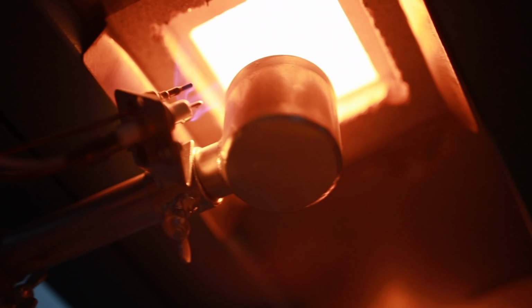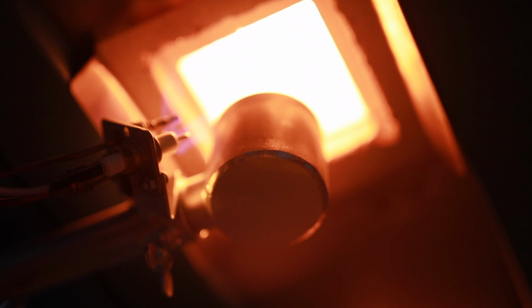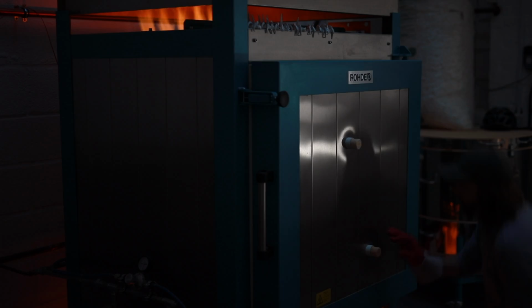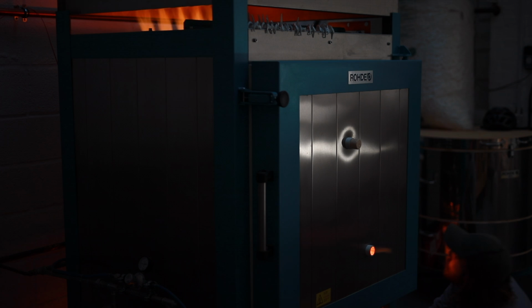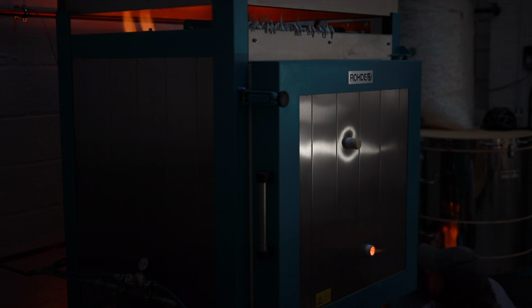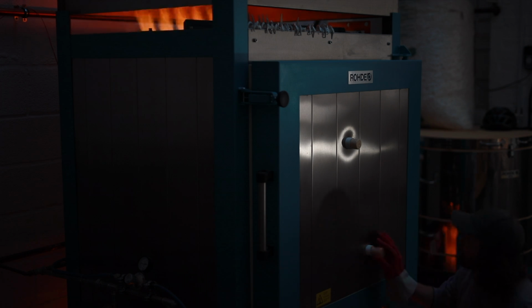My firings last for about 9.5 hours from start to finish. There are 4 burners underneath the kiln, which each jettison flame into the kiln's chamber. Slowly the temperature increases, up until my cones start to go over. I aim for about 1290 degrees centigrade, and I keep the kiln in a strong reduction atmosphere right up until the end. In this clip I'm blowing inside the kiln through one of the spy holes.